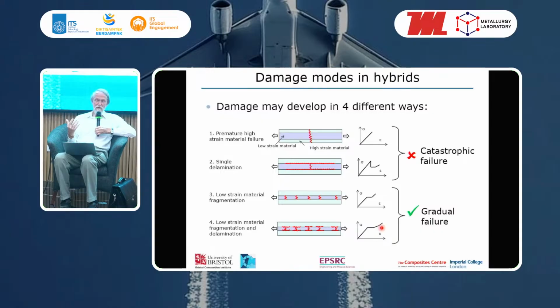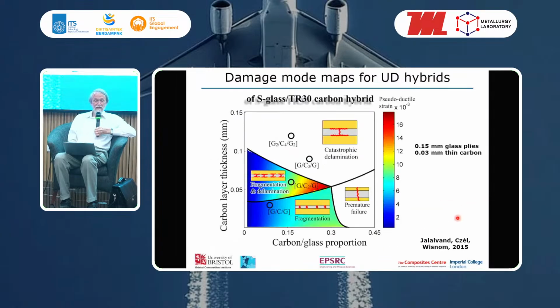So we did quite a lot of work analysing this, understanding how this works, and Mesam Jalalvand, who was one of the members of the research team, came up with these damage mode maps, where we try to understand how the different parameters which control the behaviour contribute to getting the response we want. So this is a damage mode map for S-glass and TR30, which is a standard modulus carbon fibre. And the behaviour depends on two things. It depends on the glass to carbon proportion, and it depends on the absolute thickness of the layer.